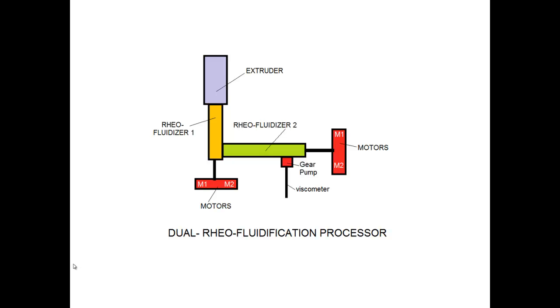There's also a large benefit on the pressure. Of course, if you reduce viscosity for a given throughput, you are decreasing your pressure, and that pressure could go from 4,000 psi to 400 psi, so a factor of 10, which of course you can use to increase the throughput and not endanger the process itself. So these being said, and I'm not insisting on that, I'm going to talk about sustained orientation, which is created